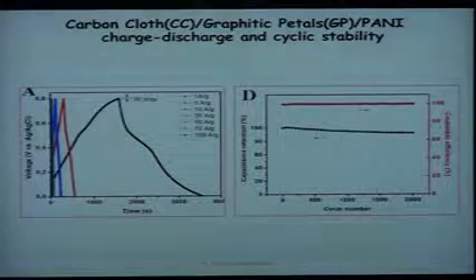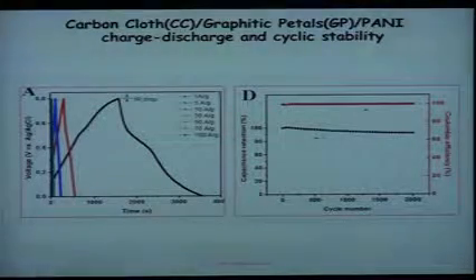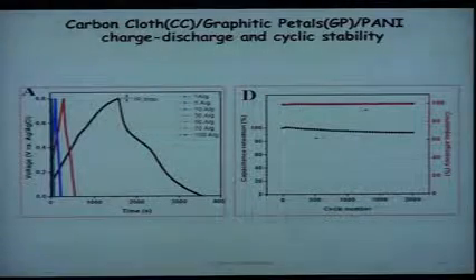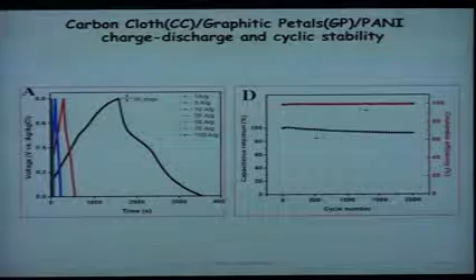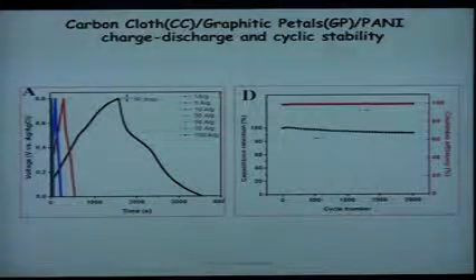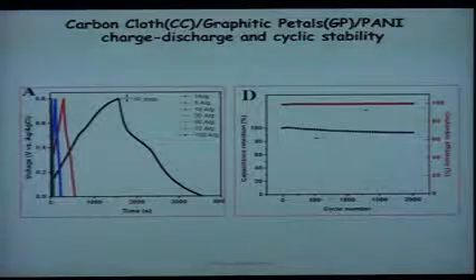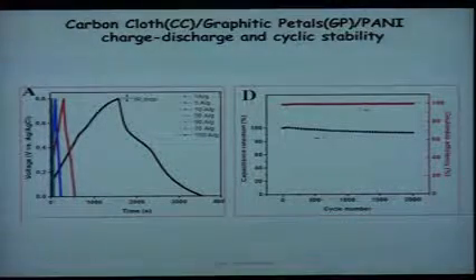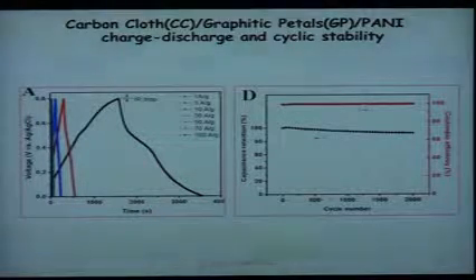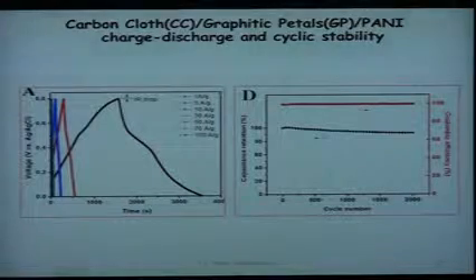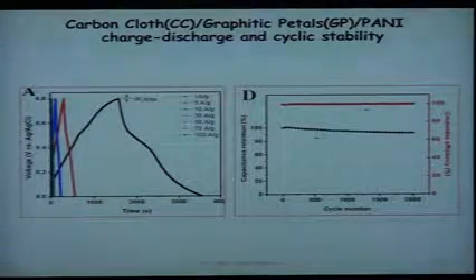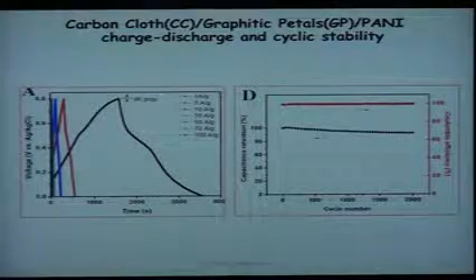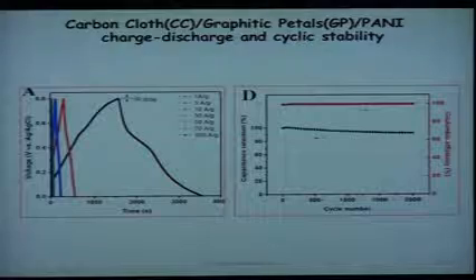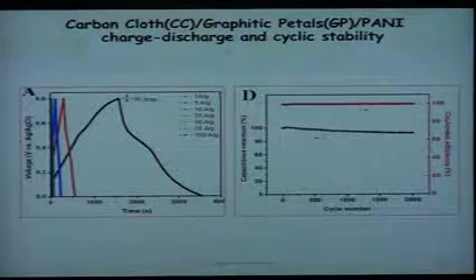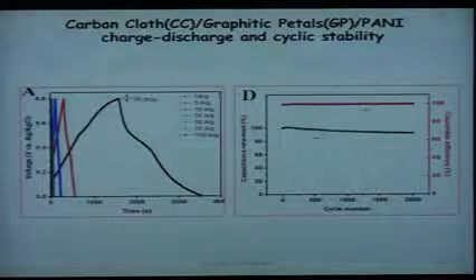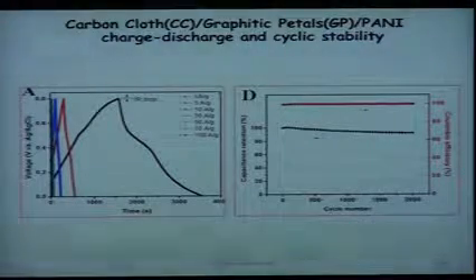In this case we were kind of comparing to batteries. Battery testing, you'd usually do a few thousand cycles to demonstrate that you have a reasonably good cyclic stability. And in this case, this is not bad, right? It looks like we've dropped about, I don't know, 8 or 10% of capacitance in 2,000 cycles. Coulombic efficiency has to do with whether all of your charge is actually coming back when you charge and discharge, and in that case, the things that can cause bad Coulombic efficiency are things like side reactions. So your Coulombic efficiency is sort of a measure of whether you're having irreversible degradation of your material.